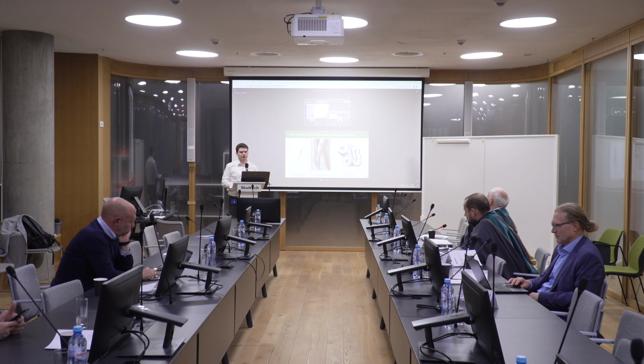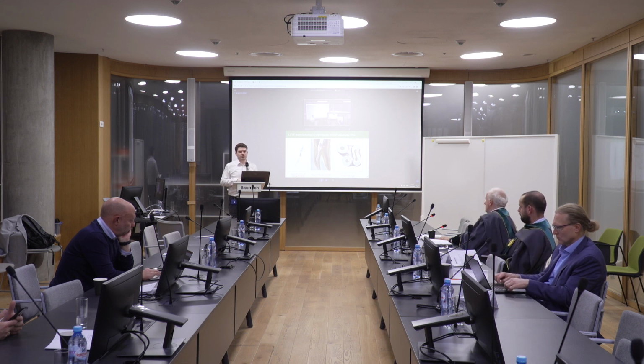So a good idea for further analysis of these micro objects manufactured by laser powder bed fusion is to put these walls into the other orientation. In this work, the building direction was studied, and we obviously have the second one. At the start of the research, I actually printed both types of samples, but as I didn't see a big difference, I switched only to the vertical orientation. But I think that maybe some effects can appear for the other orientation. So this can be concluded for the work continuation.